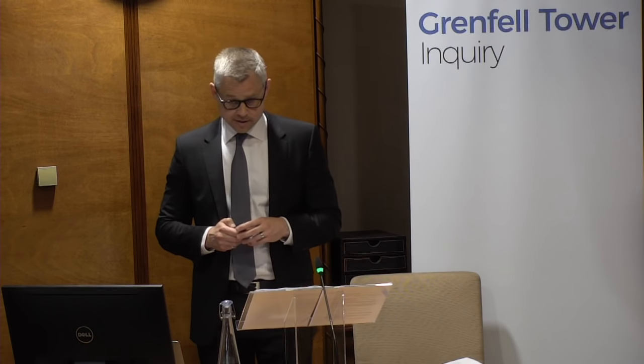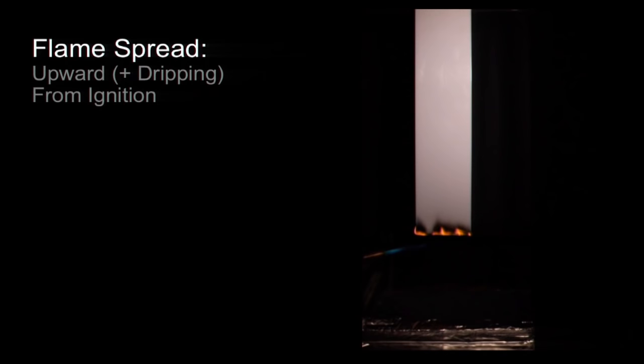This slide shows a vertically oriented sheet of a white-colored polymer. In fact, the particular polymer used here is polyethylene. And the sheet is 3 millimeters thick, and I should point out that this is a demonstration, not a scientific test. The sheet has been ignited at its base using a butane torch, and this butane torch is just barely visible as a blue flame to the bottom left of the sample. And it's quickly withdrawn out of frame.